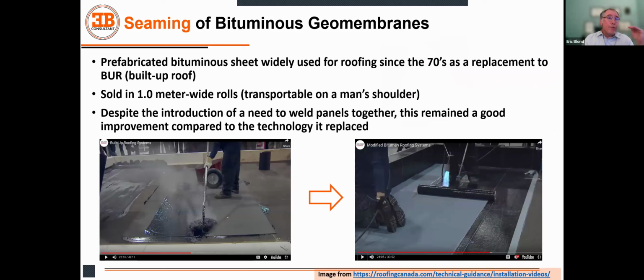First, it was built-up roof. That was a traditional solution, which was used in ancient history also to make waterproofing layers. We were pouring bitumen and layers of fabric to build a roof. Then came the innovation from the 70s, prefabricated bituminous sheet. They were sold in narrow width, 1 meter, and a lot of experience was gained with this narrow width, especially for welding. The welding techniques were refined, and it's working in roofs. My roof is bitumen. Half of the roofs around me are bitumen. So it's not something weird to see.